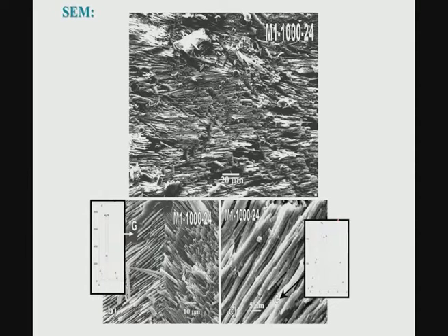Now, in terms of morphology, what we see is that these mica straw like crystals are forming not only in one direction, but also in different directions, depending on whether these materials are crystallized or ceramized at 1000 degrees Celsius for 24 hours.